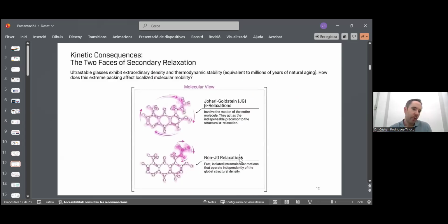Okay. Other properties which are interesting to consider when we look at the ultrastable glasses are related to the secondary relaxations, okay? You know that apart from the structural alpha relaxation process in glasses, which is mainly responsible for the formation of the glass and also for the vitrification of the glass, we have other more local relaxations, such as the beta relaxation, the Johari-Goldstein beta relaxation. Not all beta relaxations are Johari-Goldstein. And then we have other relaxations, which are more a partial part of the molecules which relax.